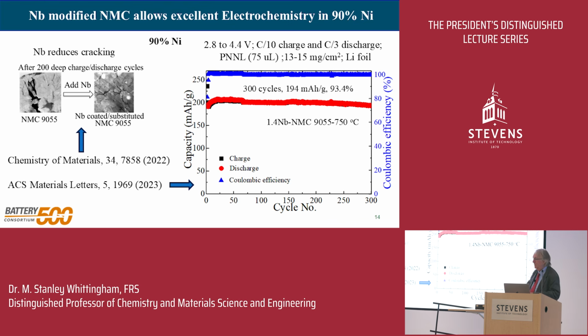So what we found out, the other way we can protect these materials so they don't react with everything that we don't want the reactions, is to do what you all do. You've got a car, you paint it so it doesn't rust. So what we do with these materials, if we add 1% niobium to them, put a coating on them, this stops the cracking, and you see on the left-hand side there, this NMC 9055 means 90% nickel, 5% manganese, 5% cobalt. You get these large cracks in it. One on the right has about 1% niobium, little cracks that don't give you any problems, but no large cracks. And you can see over here, we've got 300 charge and discharges with no loss of capacity.